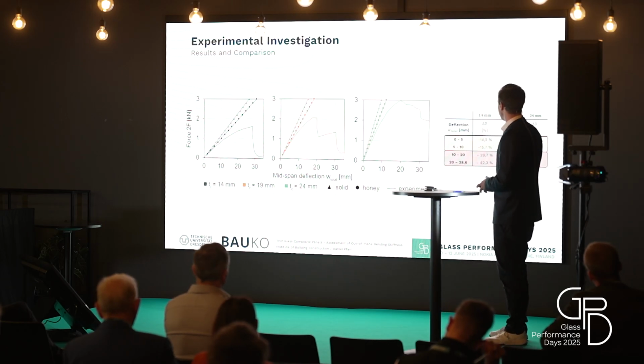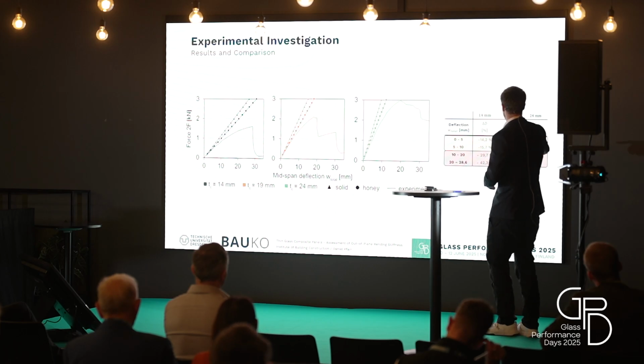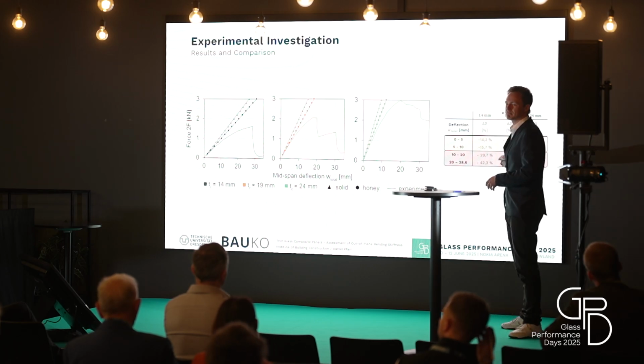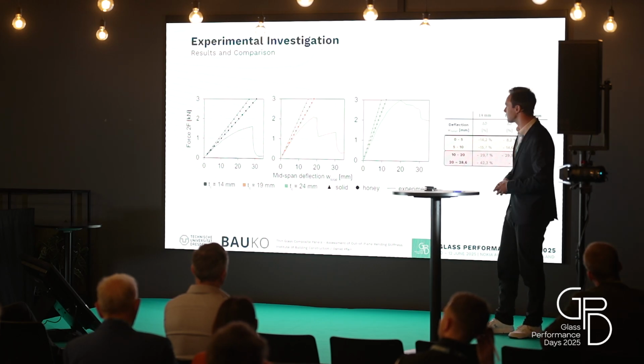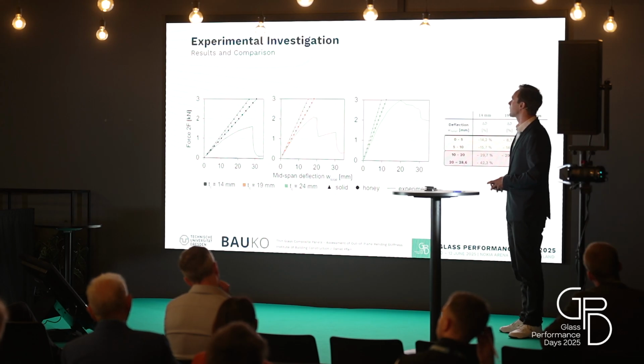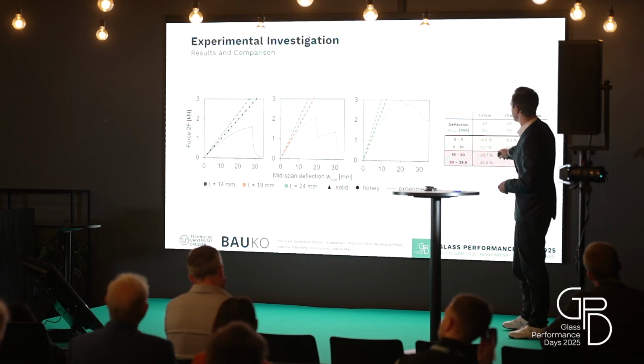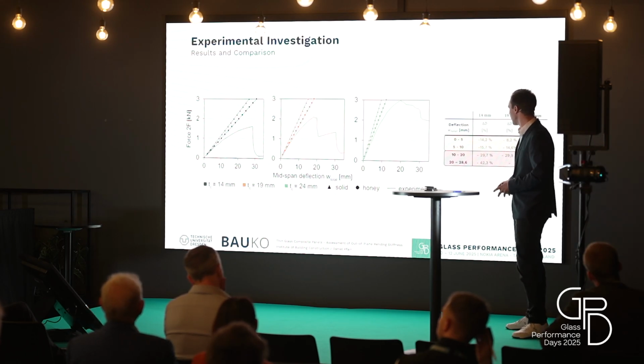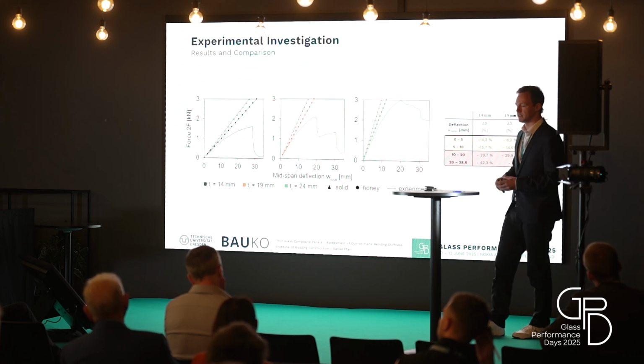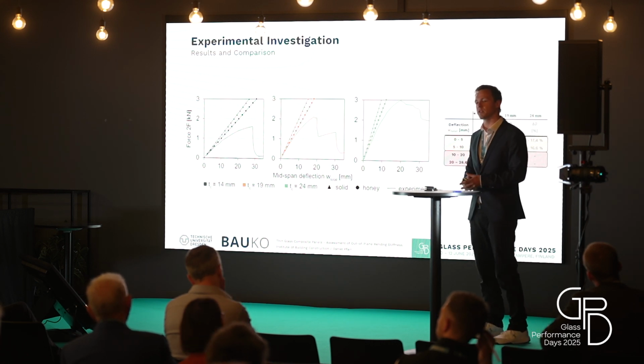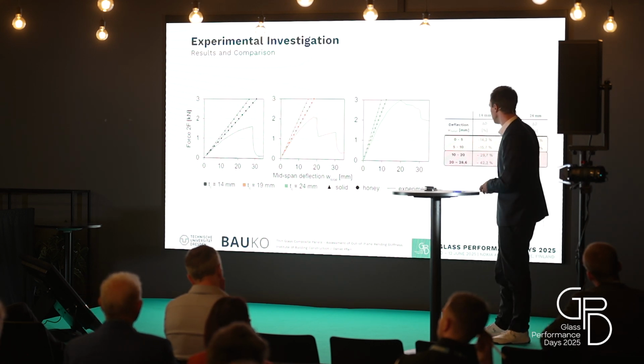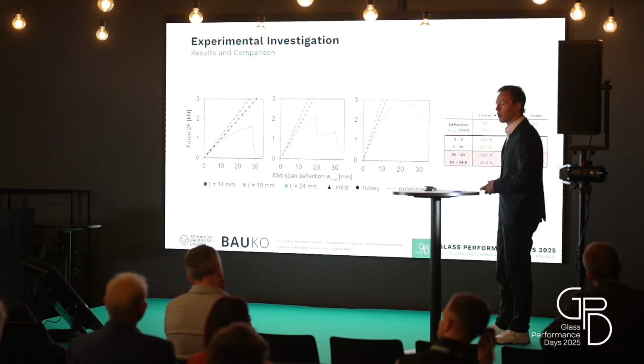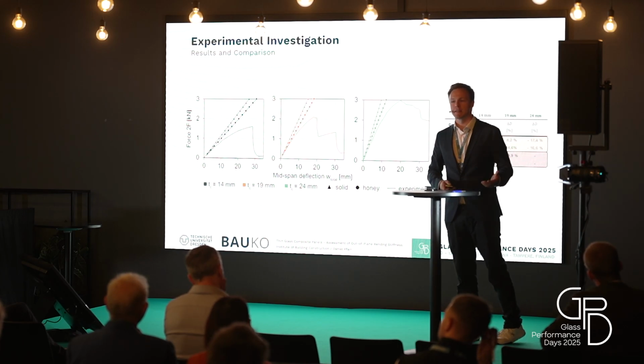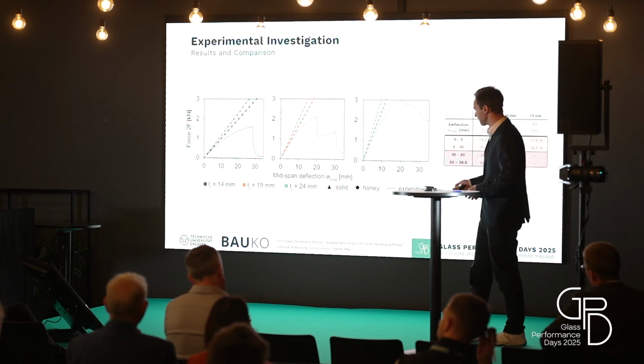If we compare the honeycomb assumption with the experimental results, we can see there is a certain area where we have a fair estimation of the bending stiffness and of the deformation, but as soon as we have a deflection of more than 10 millimeters, the deviation is just too high between the analytical model and the experimental results. So I would say that's already a fair starting point, but still some room for improvement.